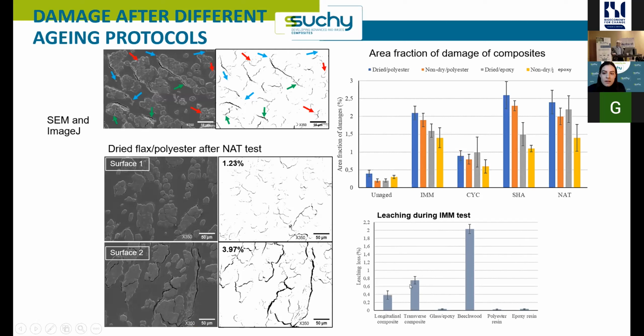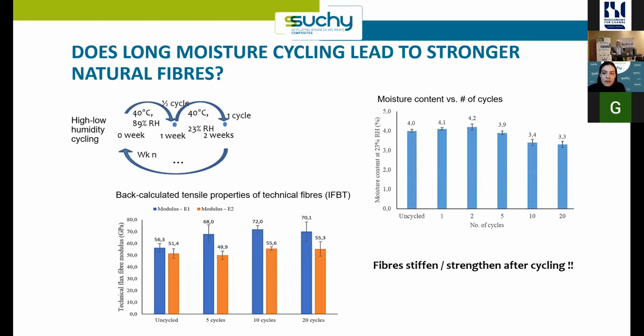We also looked at the amount of leaching for various materials, and indeed there is a substantial amount of leaching if you don't use barrier coatings. So that may be part of the explanation of the behavior, both outdoors and in immersion testing. But then this big surprise that the cyclic behavior led to an improvement in composite properties. So we also just cycled the fibers and then made composites and tested them. And indeed, you see here in blue, well, this is just the modulus results, but both modulus and strength showed an increasing tendency over the amount of cycles.